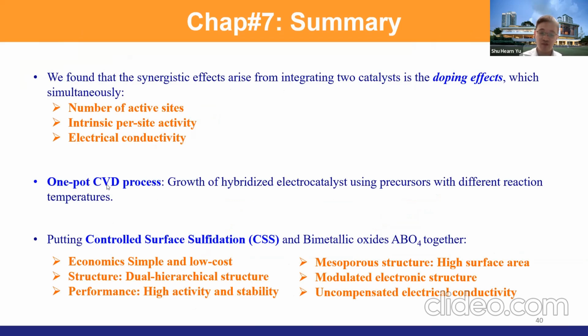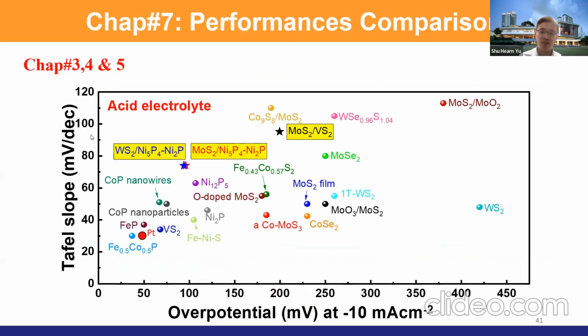And then we have a one-pot CVD process. We can hybridize two catalysts together in one step using different temperatures, the precursor temperature and growth temperature. And then last but not least, we use controlled surface sulfurization, and we apply the bimetallic oxides to get a high current density electrode. So these structures are dual hierarchy structures. They have high activity, they have high stability. So I pinpoint my material performance in this table. All the other values are from the literature.